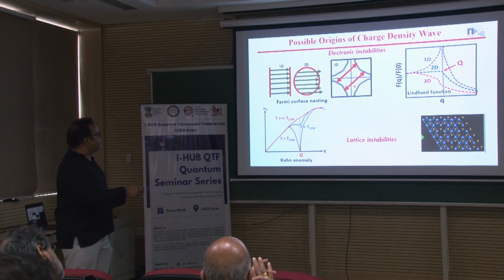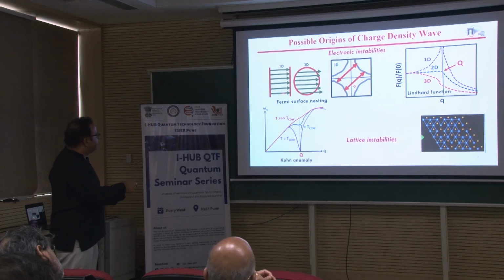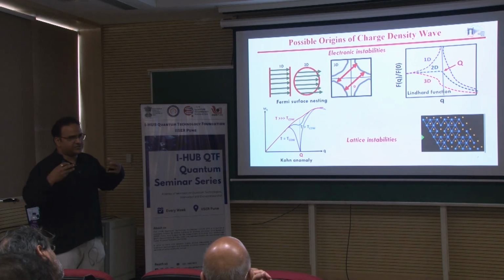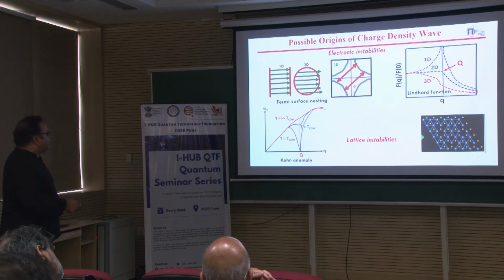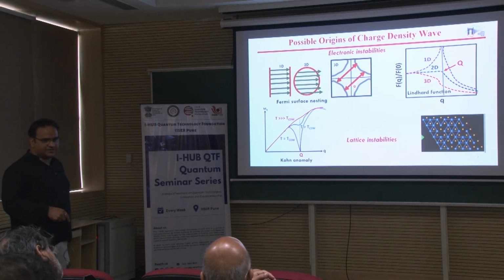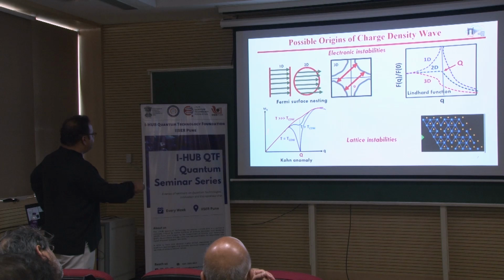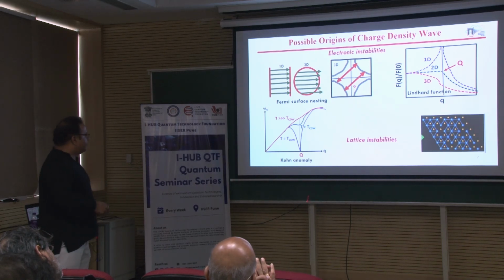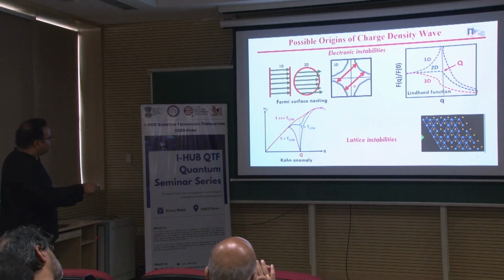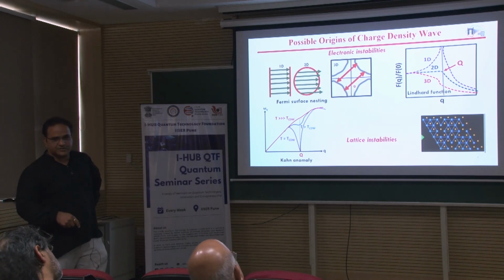So, if you look at these pictures, they tell that these are the electronic instabilities which are giving rise to the instabilities in the lattice. And now, if your material is at a higher temperature than the charge density wave temperature, you have a phonon dispersion which is the usual acoustic phonon, you can see it here. But when you go very close to the charge density wave temperature, or maybe equal to that, you have an anomaly which is coming up in the phonon dispersion curve.